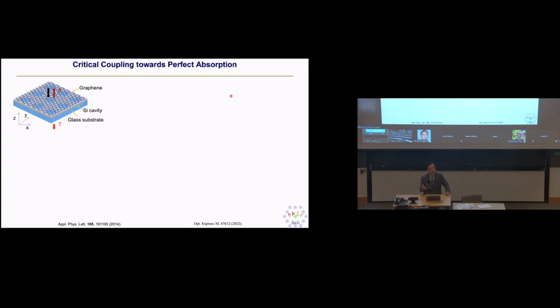The third area is, I mentioned, the absorption enhancement. In this case, it's called a critical coupling concept to get a total absorption. For example, in this case, we have a very thin layer of graphene, of nanometer range, right? So generally speaking, if you don't do anything, single pass transmission absorption is 2.3%. But if I put this graphene layer on top of my silicon photonic crystal structure, and if you design it right, that silicon photonic crystal structure is also transferred onto the glass already. So otherwise, there is no absorption if your wavelength is around 1.55, right? So the only absorption layer is a single layer graphene. And if you don't do anything, it's 2.3% if you shine light through.